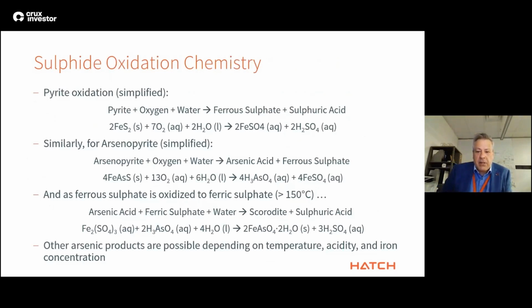A little bit on the chemistry. The first two reactions shown are the principal reactions that create heat and generate sulfuric acid and arsenic acid from the oxidation of sulfide sulfur. The third reaction, which only occurs at temperatures greater than 150 Celsius, is the conversion of ferric sulfate and arsenic acid to scorodite, a stable form of arsenic. And I want to talk a little bit about this because it's important for what's to follow.